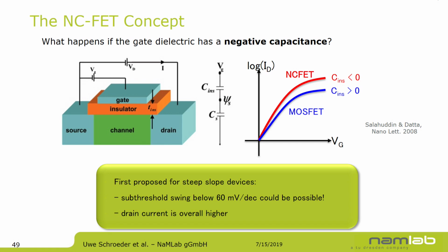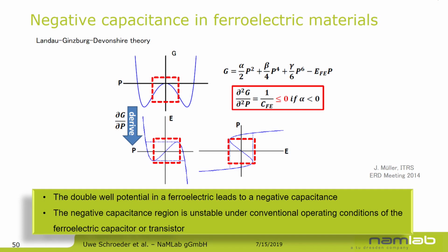improve your subthreshold slope. And the main discussion was always, well, if I shrink down the thickness of the hafnium oxide to what's currently in high-performance transistors, in this 2-3 nanometer range, it's really unclear if you really have ferroelectric properties. There are PFM studies done on the topic, but still the discussion was ongoing. Do you really see a negative capacitance effect? So we looked into the topic and wanted to prove that this is possible.